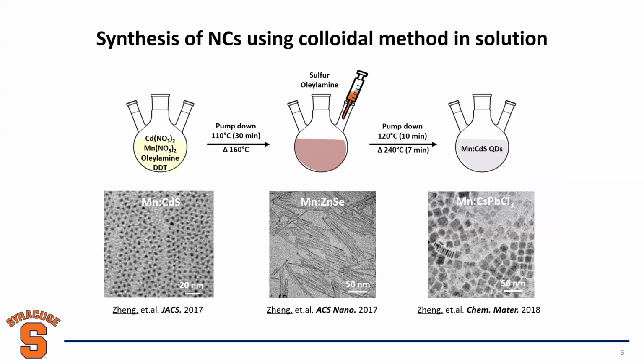Okay, here I show you a couple of examples. We use the colloidal method to make magnetic nanoparticles. The example here is manganese-doped cadmium sulfide quantum dots. We introduce magnetic dopants there. We introduce impurities into nanoparticles. You might ask, why do you want to introduce impurities? Are impurities bad for nanomaterials? Well, it depends, right? If it's a bad impurity, we usually call it a contaminant. If it's a good impurity, we call it a dopant, right? The modern semiconductor industry spends $1 trillion every year trying to make N-type and P-type doped semiconductor materials for electronic devices. So we introduce good impurities called dopants.